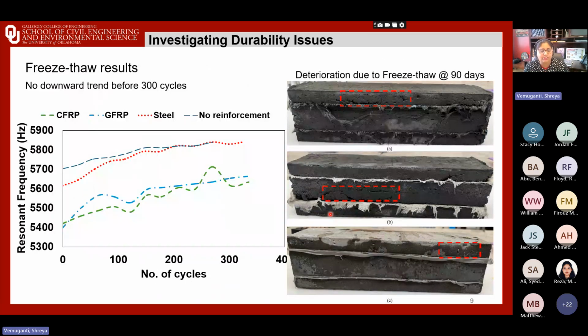Moving on, I want to dive into the results of this particular specimen testing that we performed. If you look at the freeze-thaw results, we have the resonant frequency on the y-axis here, and the x-axis is the number of cycles. After repeated freeze-thaw cycling, the specimens you see here represent some aggressive deterioration environments. On the right, you can see these cross-sections of failed specimens and these red boxes highlighting cracking